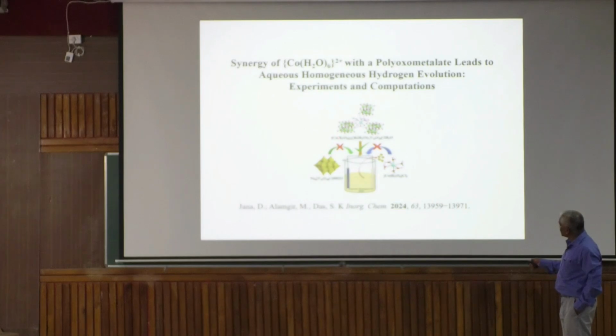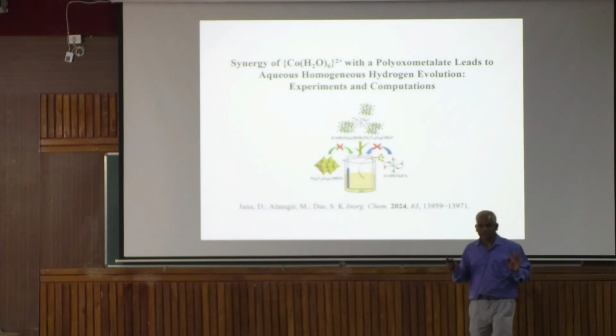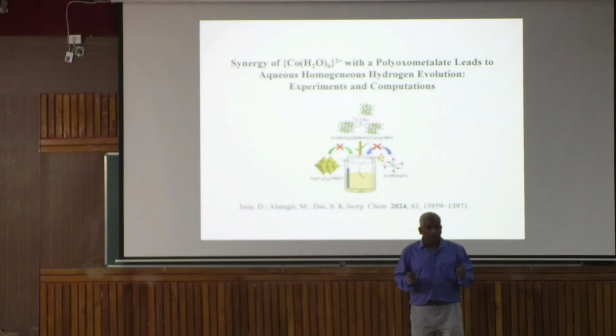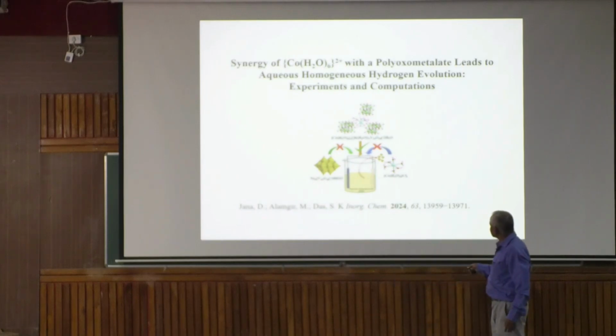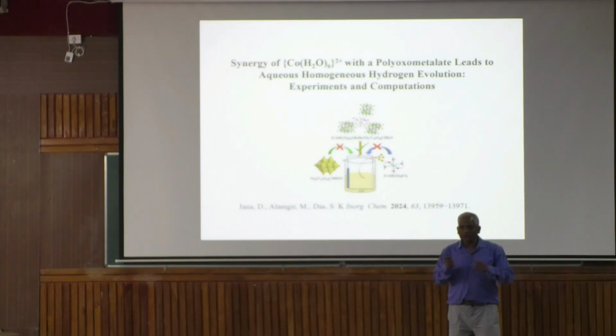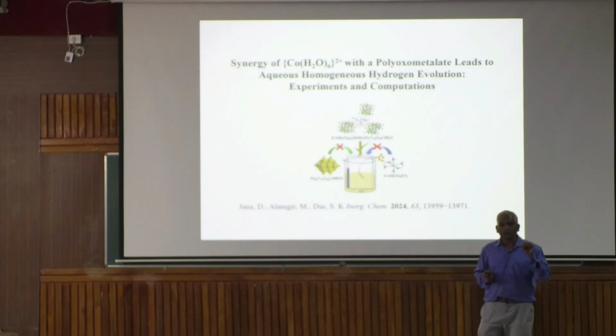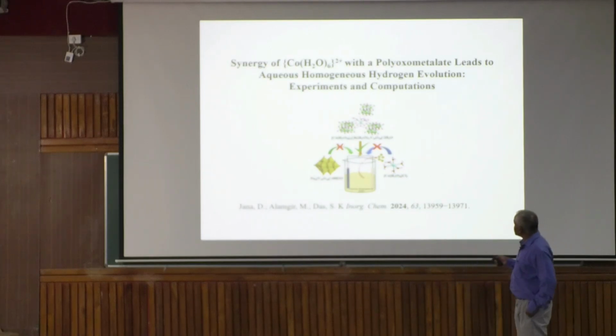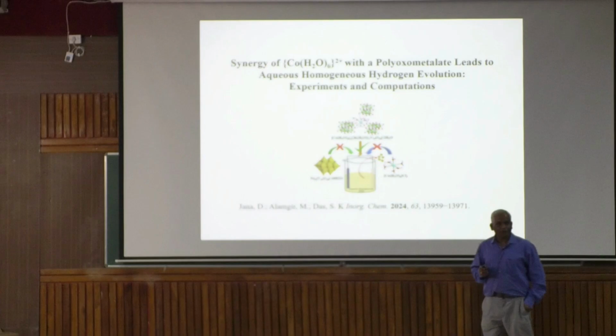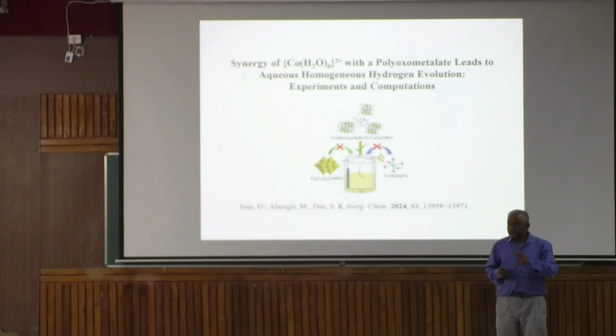So these two compounds, as if I put them in a crystal. So if you put this compound in water, it gives homogeneous water oxidation. If it is really true and that too homogeneous, then why do you have to make this? You take sodium bicarbonate, you take cobalt chloride and put in this proportion, you should get continuous oxygen. It doesn't come. This is the beauty of supramolecular chemistry. Why? When we solved the crystal structure, we found a very, very interesting hydrogen bonding network between this cobalt aqua and decavanadate. Not only that, we took the mass spectrum of that. Okay? And the same mass is maintained.